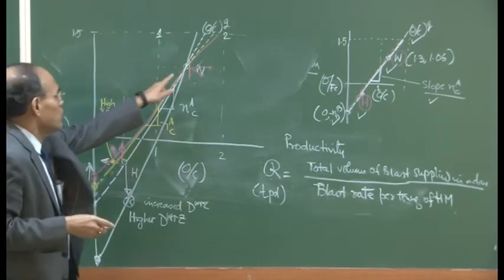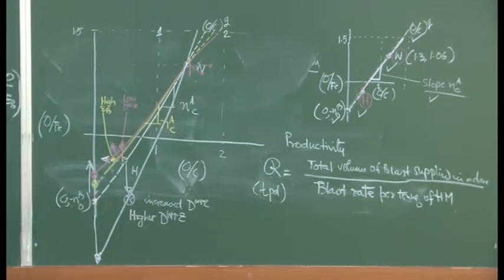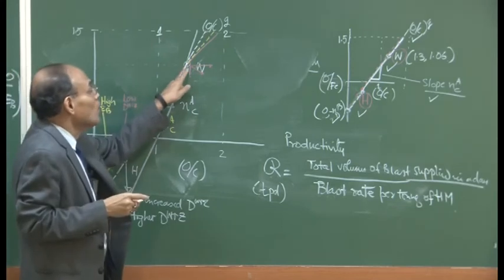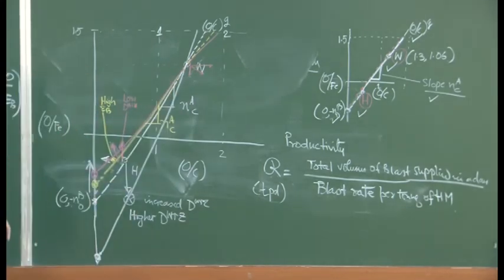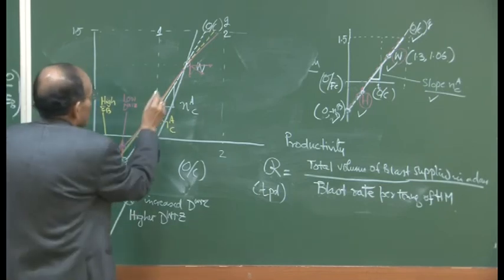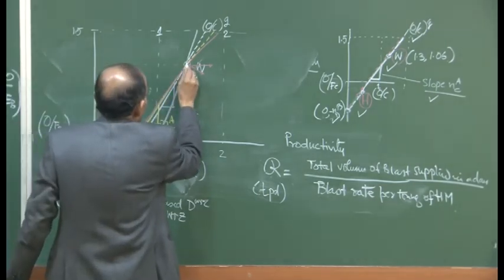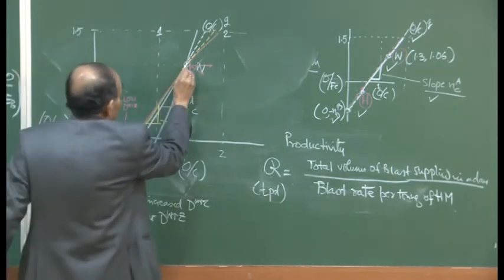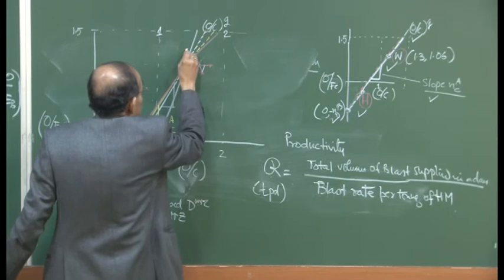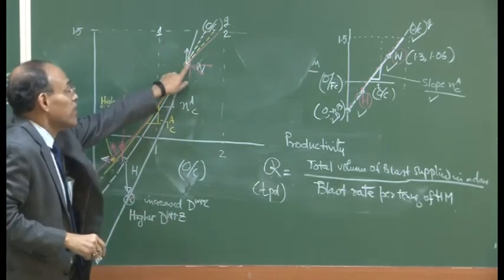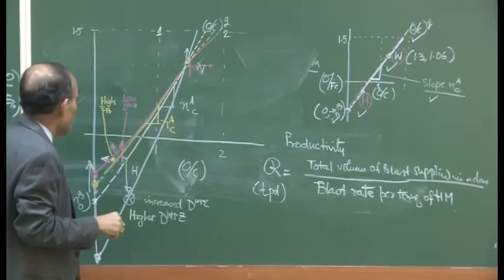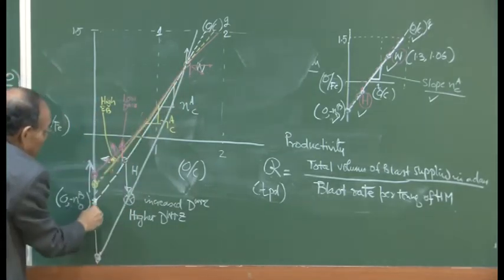What about the point W? The 1.06, of course, as I have indicated, will depend on the ore. For example, if you have silica reduction, manganese reduction, phosphorus reduction, that 1.06 could become 1.16, 1.17, 1.18 and so on. So the impurity present in the ore will affect this, and if you assume that 1.3 remains constant, this point will try to move. For an ideal case it is 1.06 here, but for an actual case this point is going to move, and as a result the line becomes more steep.